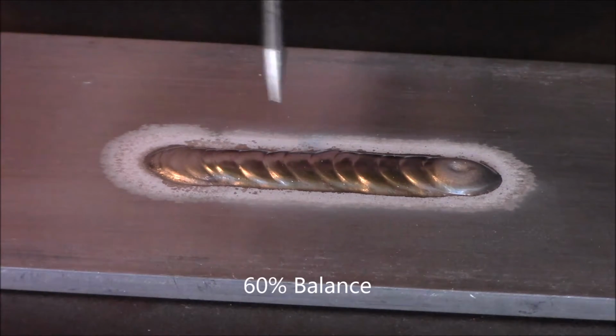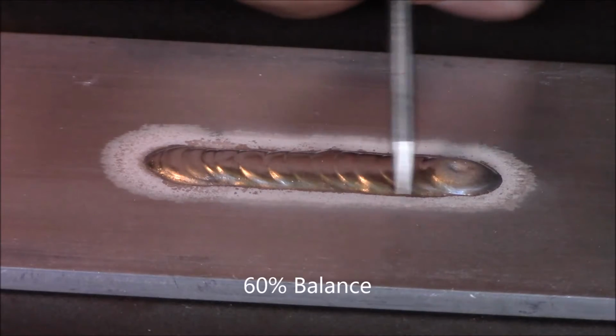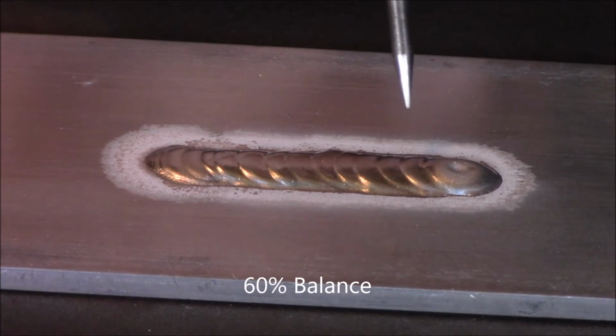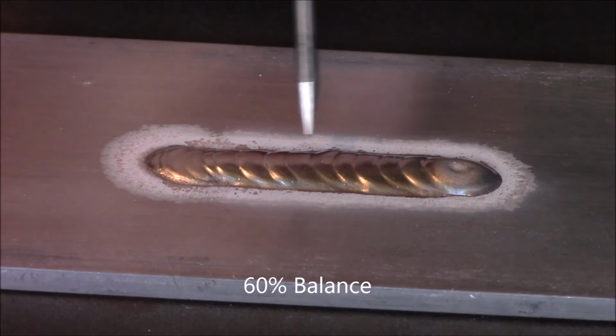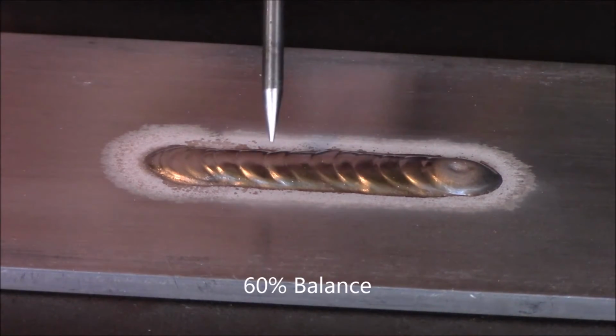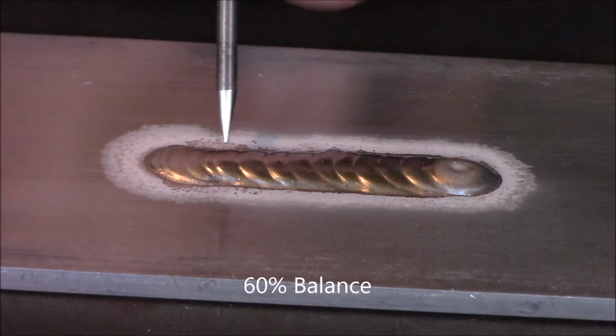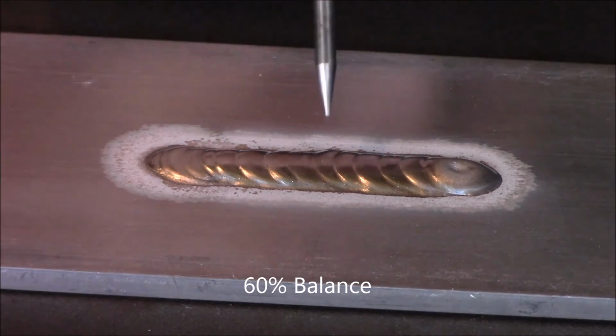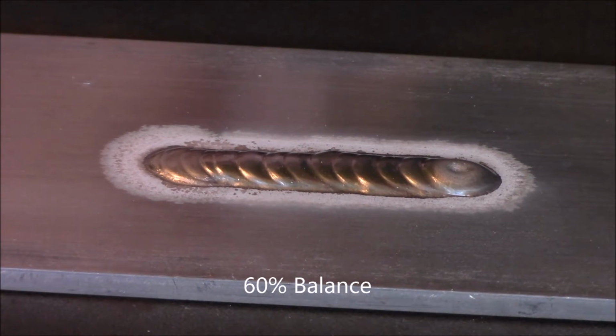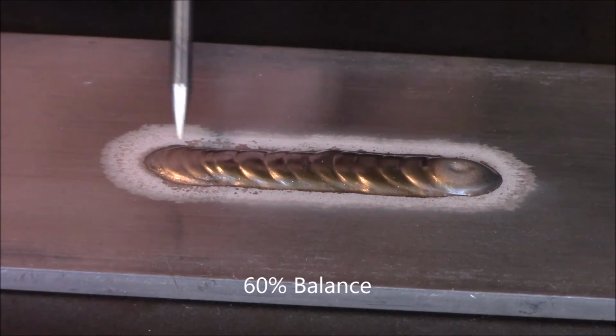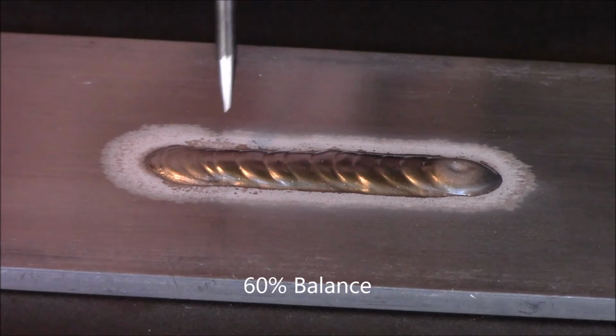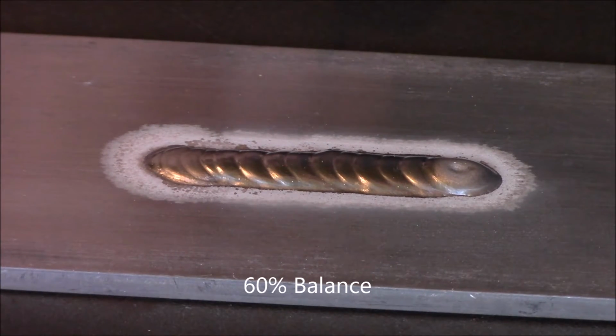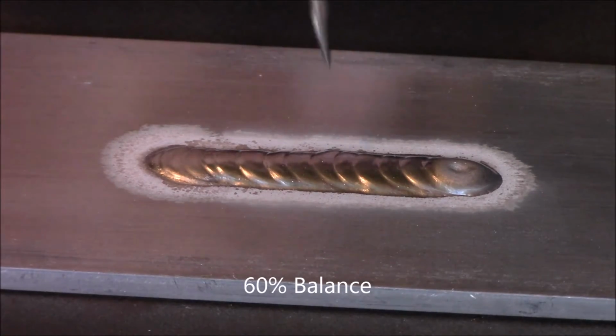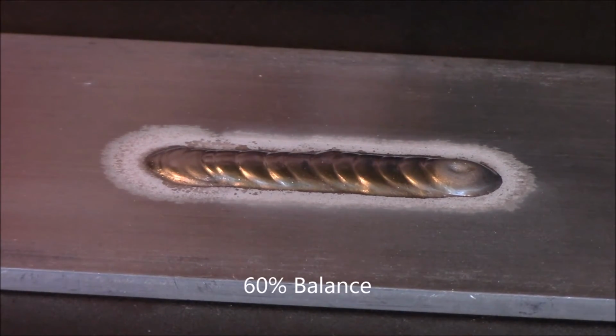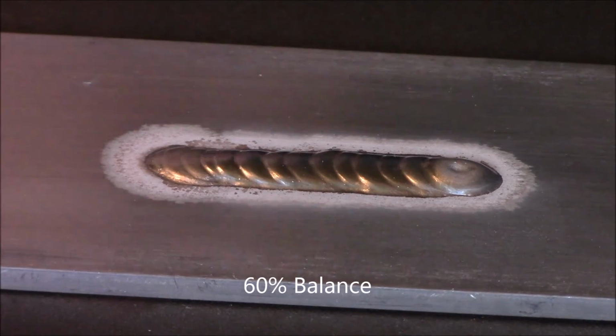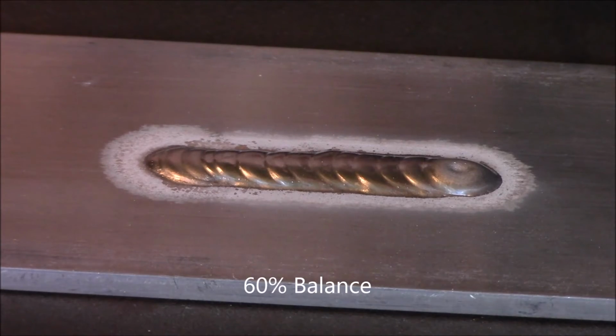Finally, we've got 60% balance, which as you can see is a very dense, much wider etch zone all the way around. Now that etch zone in itself is not necessarily detrimental to the weld bead, but what you would have over time is considerably more balling of the tungsten, and you can see it's a little bit hazier than the previous one at 75%. That's because the electrode positive, the ionic bombardment that occurs in that part of the cycle, is just a little bit more energetic than necessary. We're spending a little too much time there, so we're hazing over our weld just a little bit. So all that being considered, if I were doing this, I would select 75% as the better of the three here. You could hone it down a little bit more, but for the sake of being quick, that should suffice.